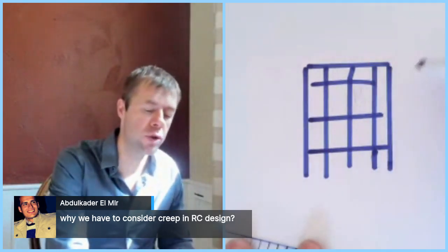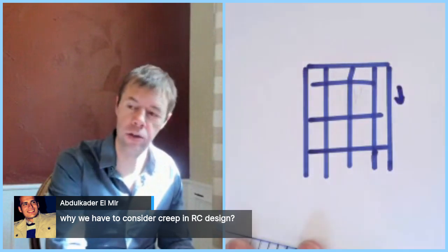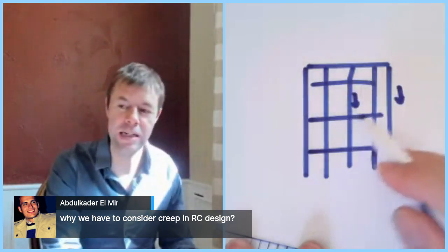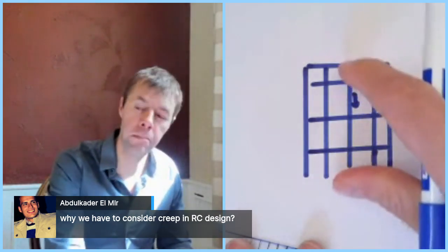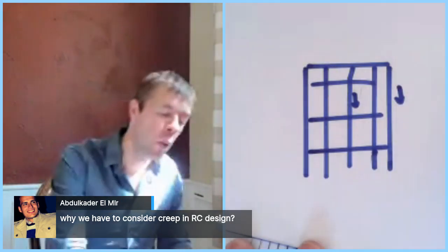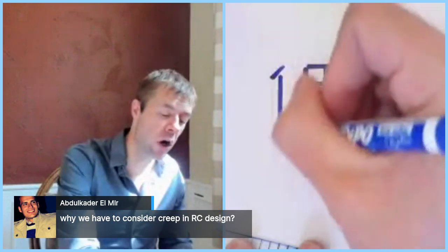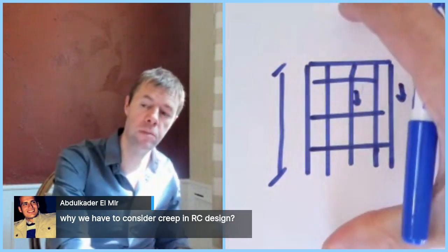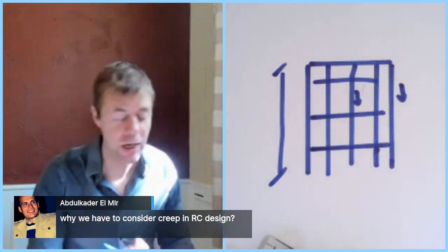Now, if I have a lower axial load on the outside than I do in the center, I will get differential shortening in my building. I will get more shortening in the middle than on the outside. You might say, well, does this really happen? Yeah, it really does. And it's much more of a deal in tall buildings, because even though there's not that much deformation, they deform over a much larger length. So you can get differential shortening of inches on the top stories of buildings between the inside and the outside just caused by creep.